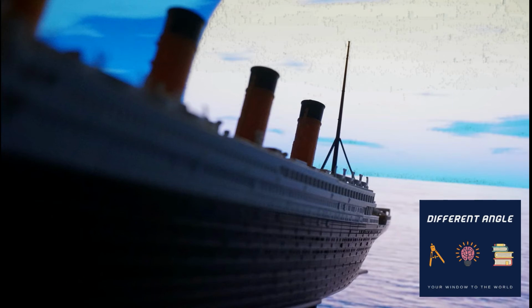In the search for answers to the question, why did the Titanic sink? The steel from the Titanic was further analyzed for chemical components and was found to contain high levels of both oxygen and sulfur, which implied that the steel was semi-killed, low-carbon steel, made using the open hearth process.